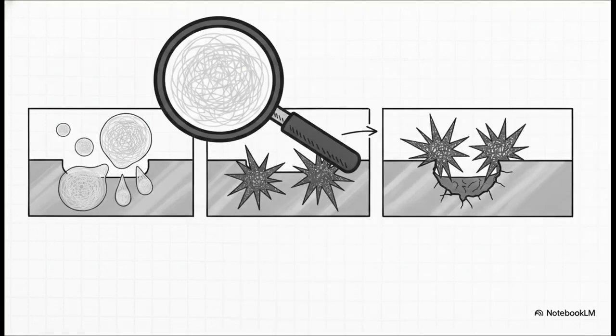Chemically, this builds up through a relatively slow process. First, the CO2 dissolves into the produced water. Next, that dissolved CO2 hydrates to form carbonic acid. This drops the pH of the water, turning it into a weak acid that aggressively eats into the carbon steel wall. And over time, instead of just a uniform, even loss of metal, this often forms localized pits. These are essentially deep craters that can rapidly compromise the structural integrity of your entire pipeline.